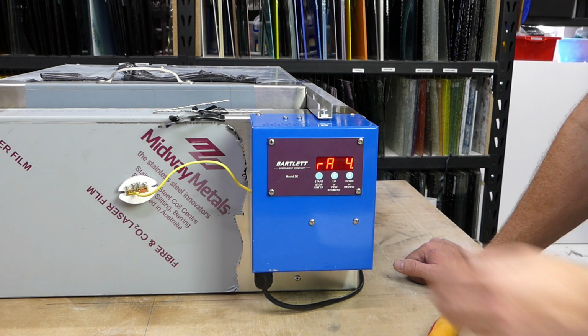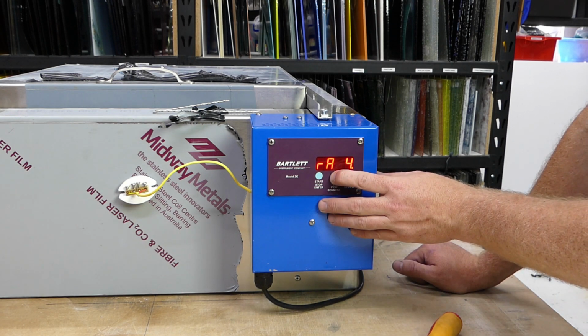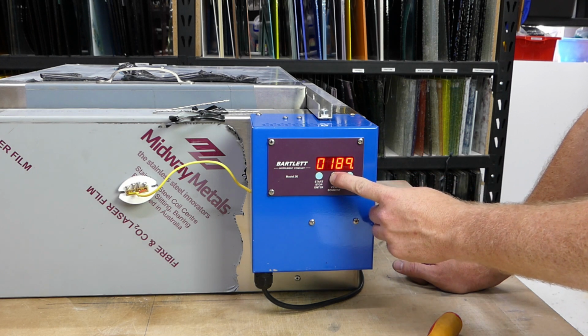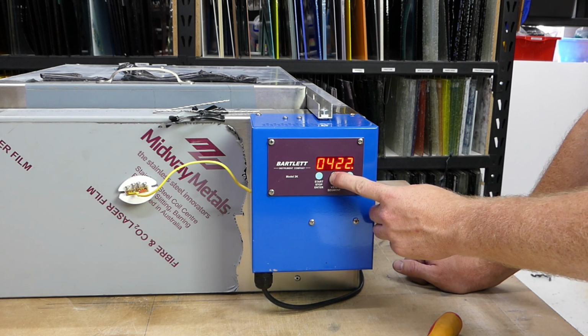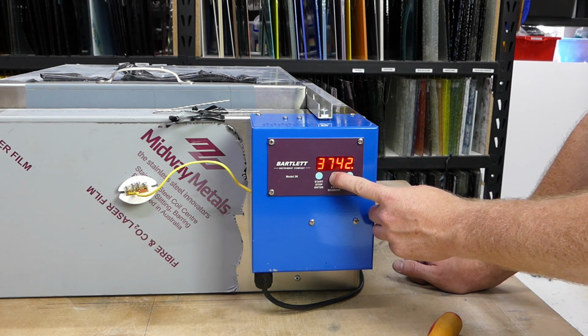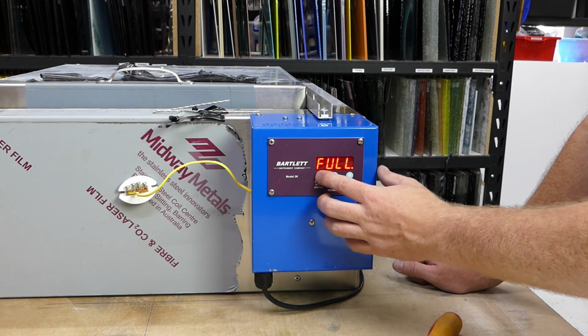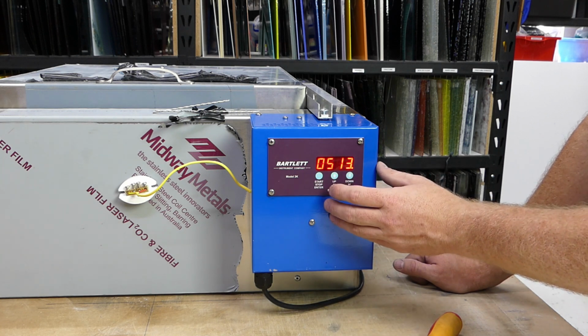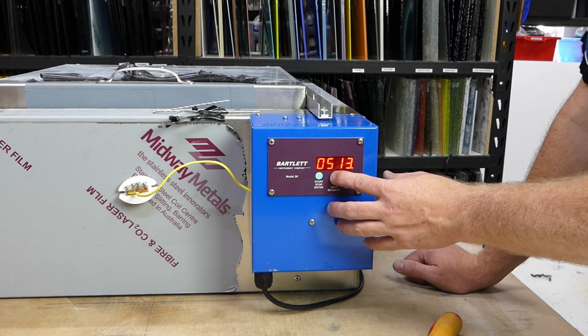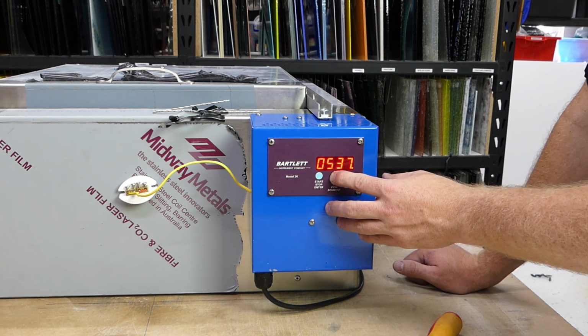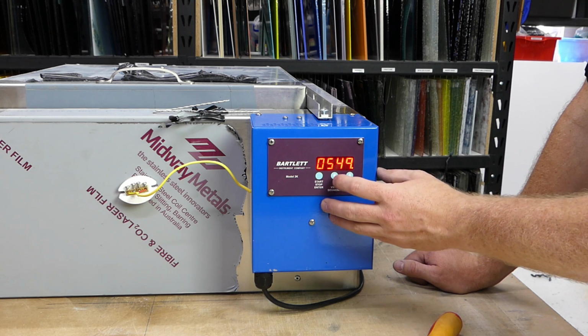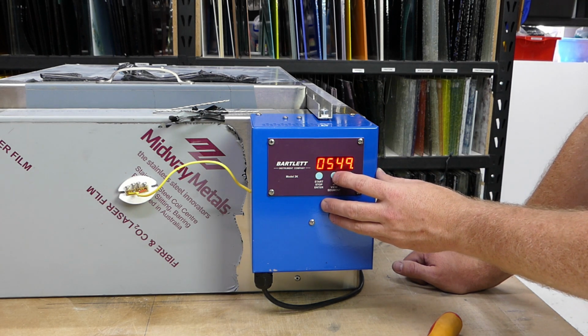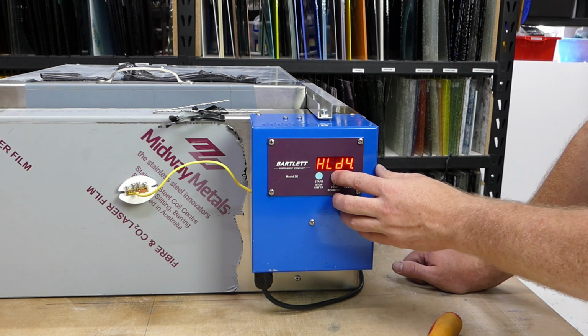And now we're starting to ramp down. So we're going to go down at full speed. So we just press and hold the up key until it says full. It will just take a minute. Full. And we're going to drop that down to the first annealing point, which is 550 degrees. We're going to hold there for 30 minutes.